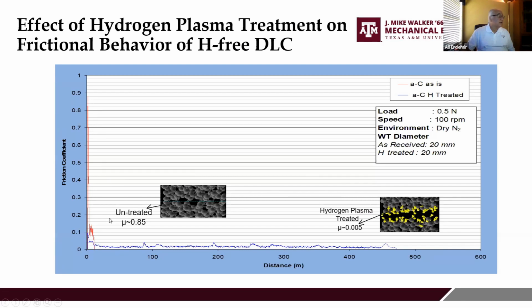0.85 and higher. But after the surface is fully hydrogenated through this hydrogen treatment or bombardment, that surface started giving this extremely low friction coefficient, as shown in the blue curve. In fact, we could measure the friction coefficient down to 0.005. So the hydrogen termination of these carbon surfaces or DLCs turned out to be a very important mechanism to achieve superlubricity.